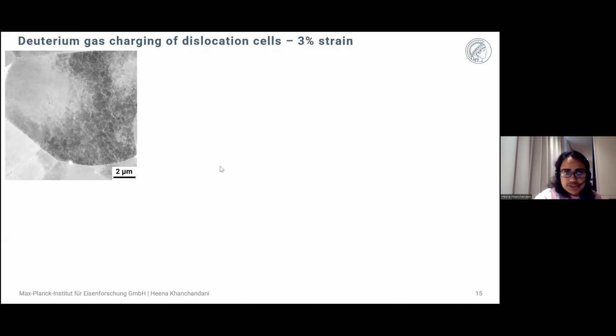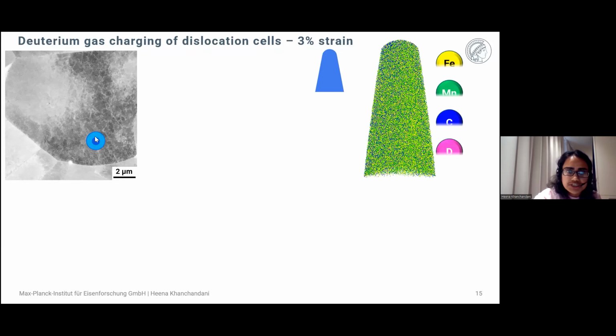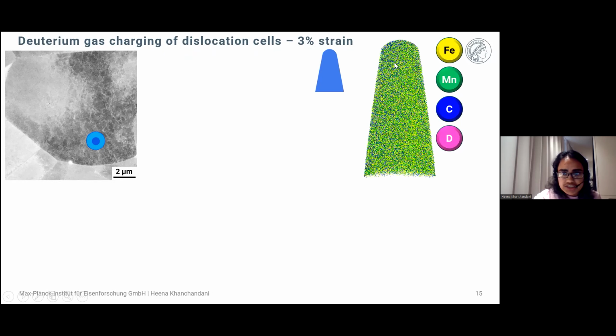And then we performed a similar analysis on the sample with dislocation cells, which were formed in the 3% strain sample after hydrogen charging. So we prepared an APT specimen from the region containing a very high density of dislocation cells. But we could not find any deuterium segregation at any specific microstructural feature. It could also be because the samples were already charged first with hydrogen and then they were subjected to the tensile test. So possibly all these sites could be occupied by hydrogen.